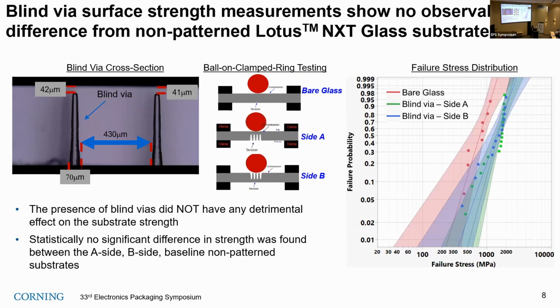So there were a lot of doubts. Glass has a certain strength. Can this blind via impact the strength of the glass during this complex TFT fabrication and assembly? So we did some tests. One of the tests is called the ball on clamp ring test, which we use to study the surface strength of glass substrates. We did different combinations: bare glass, and vias on side A and vias on side B. The plot shows the failure probability distribution, which shows the failure probability of the samples and the likelihood of their occurrence.